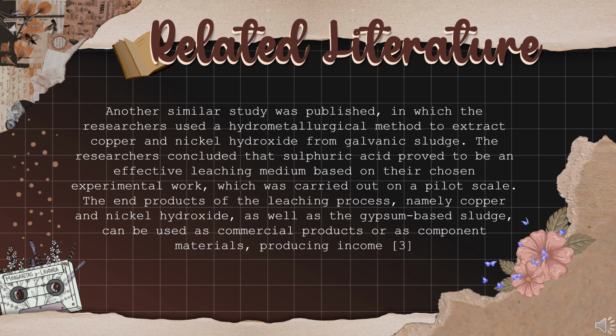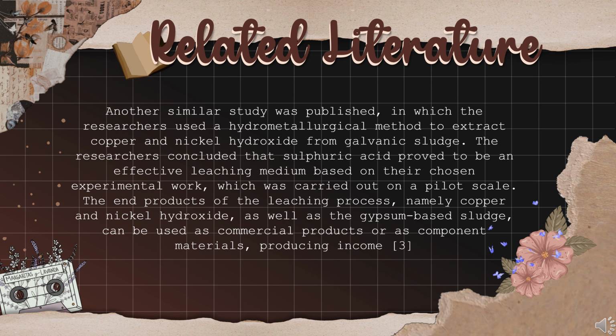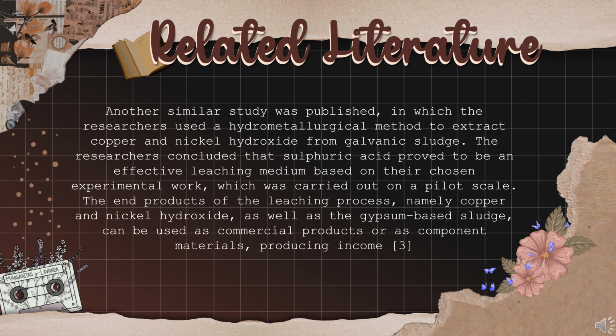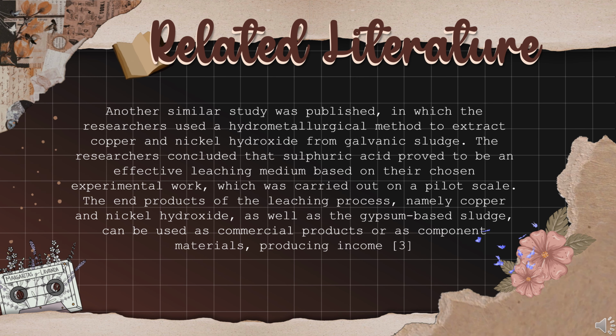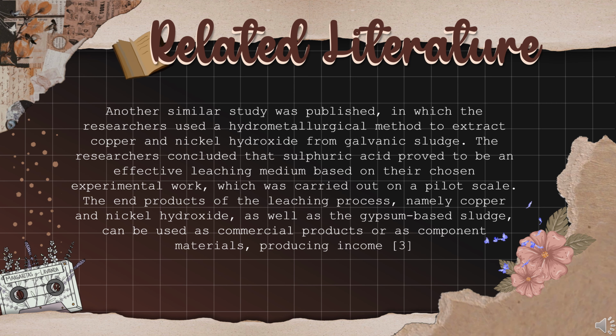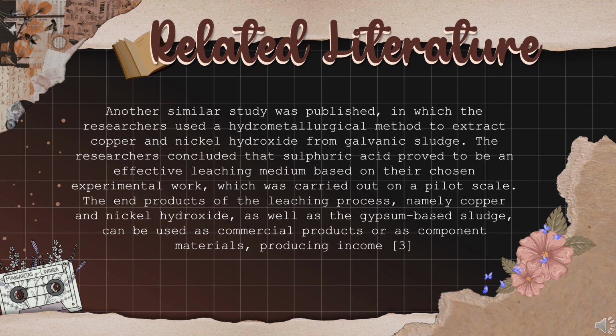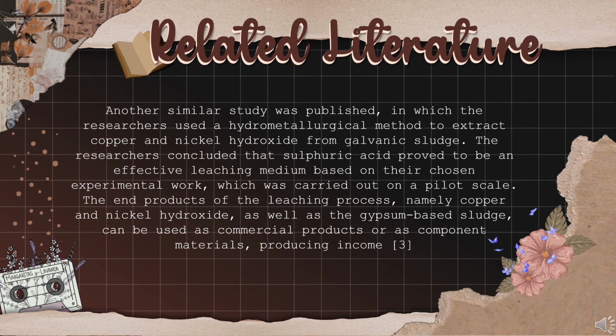Another similar study was published in which the researchers used a hydrometallurgical method to extract copper and nickel hydroxide from galvanic sludge. The researchers concluded that sulfuric acid proved to be an effective leaching medium based on their chosen experimental work, which was carried out on a pilot scale. The end products of the leaching process, namely copper and nickel hydroxide, as well as the gypsum-based sludge, can be used as commercial products or as component materials producing income.